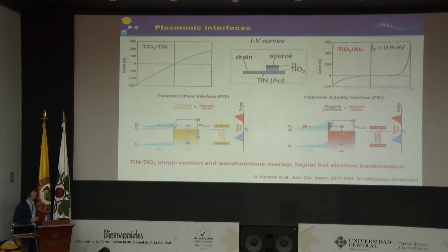And therefore, we did some electrical measurements, and we saw indeed that in contrast to gold, where of course we saw the normal formation of a Schottky barrier between the metal and the semiconductor, we saw a kind of formation of ohmic junction between the titanium nitride and titanium oxide. Maybe it is not really an ohmic junction. There is a small potential barrier, but anyhow, it is really very much smaller than what is formed in the titanium oxide.